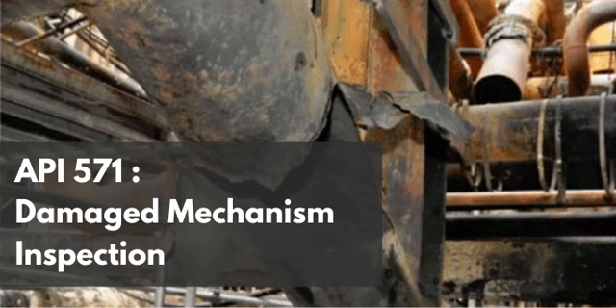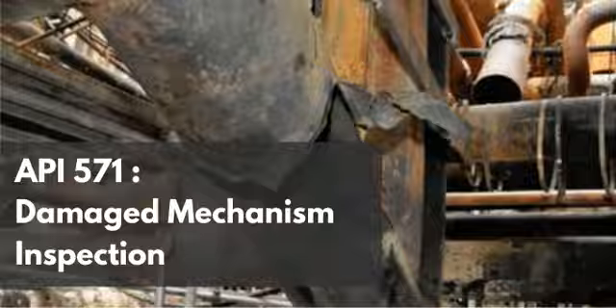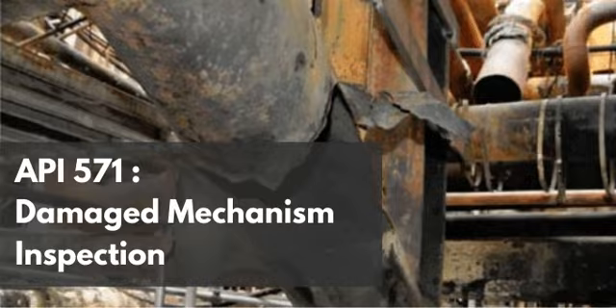When the chromium is severely depleted from the surrounding matrix, the local crystal structure of the iron can no longer maintain its specific face-centered cubic austenitic phase. It shifts. It becomes chemically unstable. The atoms literally rearrange themselves and physically transform into a ferritic or martensitic phase. And both ferrite and martensite are highly magnetic structures. That is incredible. The invisible chemical theft of the chromium literally reveals itself through magnetism.